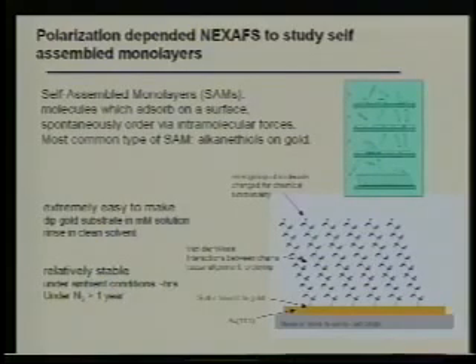And the interesting thing, on the top plot, is if you put your gold substrate in a solution of these materials, what's going to happen is over time these materials bond to the surface, and they bond and they lay flat originally.